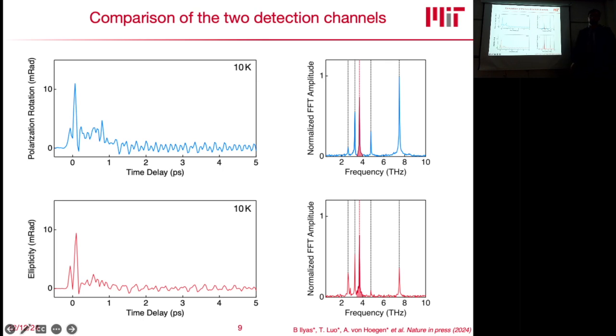And every time you measure a certain delay, that's a separate experiment? That is basically a separate experiment, which takes about 30 milliseconds. So you sit on a point, you integrate for 30 milliseconds, then you go to the next one, integrate for 30 milliseconds, and you repeat this a couple of times. Taking one of these curves from 0 to 150 picoseconds takes about 20 minutes. So it's actually not too bad. And this is the signal to noise of one of these scans. So it's already decently high. For this material; for other materials, you will need to integrate a little bit longer. Did that answer? Okay, perfect.